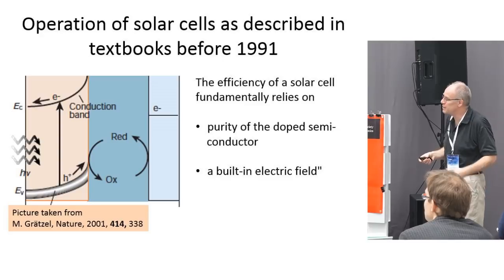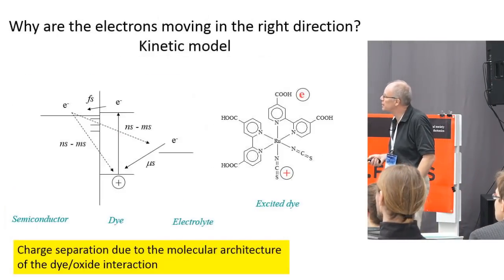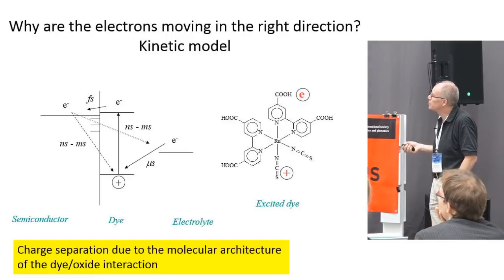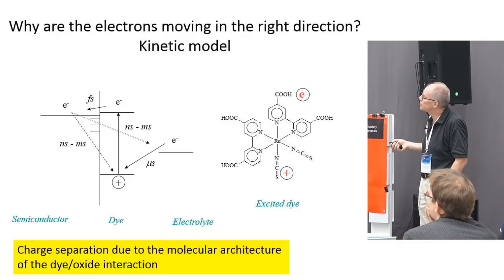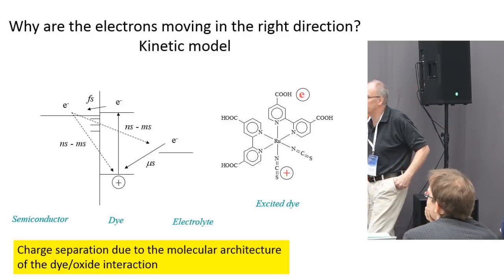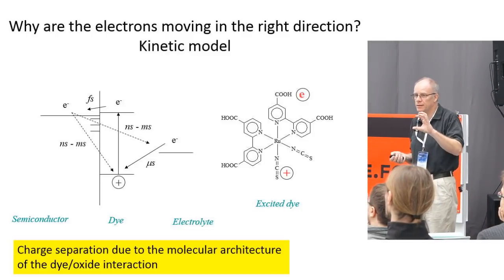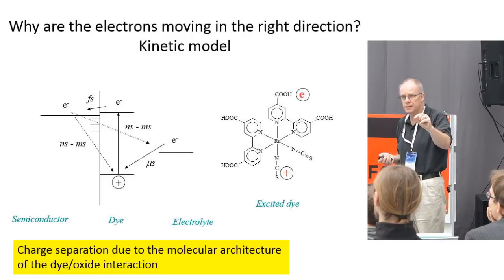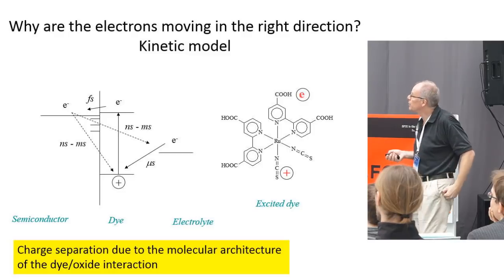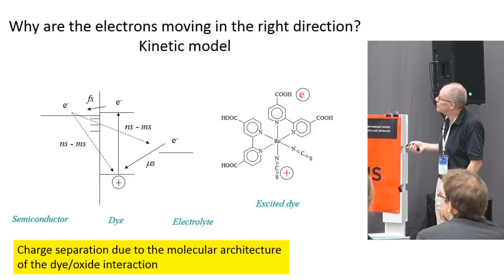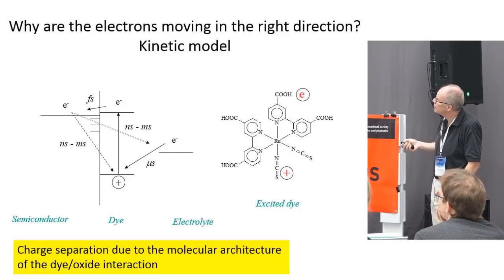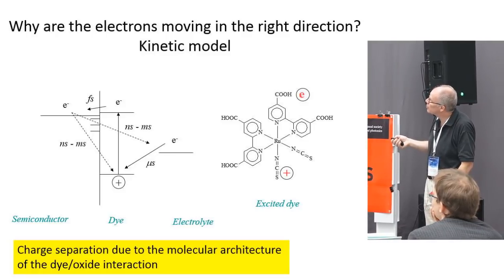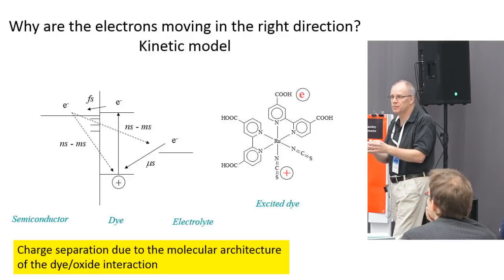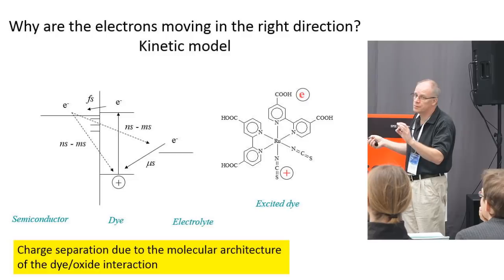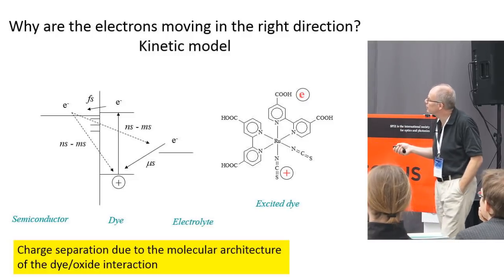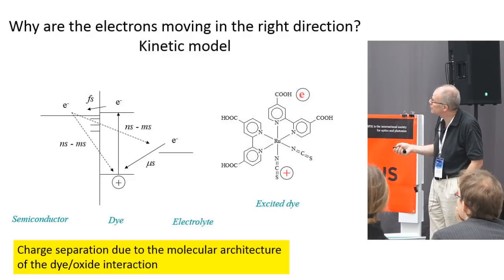So we took a much more chemist view on things. And for the charge separation, we studied the dye molecule in terms of quantum chemistry calculations, synchrotron radiation, mapping out the orbital structure. And the question was, when we excite the dye, where is the electron in the excited state locally? Where is the hole? And we could then, through this study, see that when we excite these kinds of dyes, the excited state of the electron, this one here, is located on the carboxylic group. And that's perfect, exactly where we want it to be, because that's where we have the anchor to TiO2. And the hole, the oxidized state, is mostly located on these sulfur atoms on the ligand.